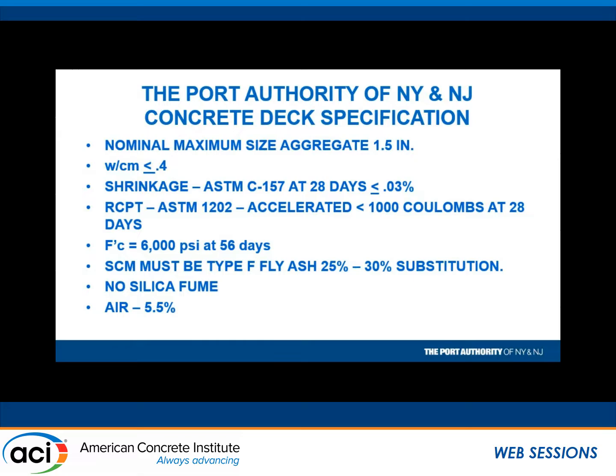One requirement that we had in our spec was you will use 1.5-inch aggregate. Now again, people say, well, you shouldn't do that. But we have found through the years that the larger the aggregate, the more coarse aggregate you have in there, the less cracking you get. This isn't something that we need to research too much anymore, and yet there is a great reluctance to do this. This turned out to be an unbelievable wrestling contest with the contractors. He didn't want to do it because of difficulty in pumping 1.5-inch stone, difficulty in finishing it, difficulty in consolidating. All of them turned out to be not true when all was said and done. And we did use 1.5-inch aggregate.